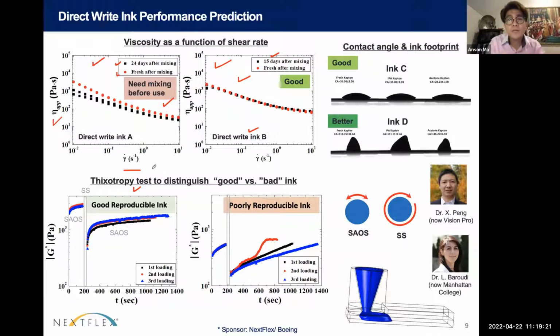That has to do with the fact that the ink usually contains particulate materials and some kind of microstructure. When you shear the material, you modify the structure. But after you shear the material, if you let it sit again, then the viscosity could recover. And sometimes the viscosity could be even higher than your starting point. So in that case, you would say, well, what is going on, right? So this is a test method that you can use. It's one of the ways to do thixotropy tests.